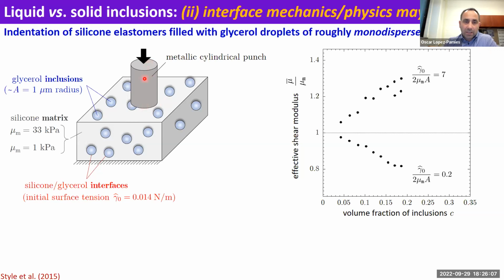So this is indentation of a block of material that contains liquid inclusions. And by changing the size of the inclusions or the surface tension, you may end up with systems that are stiffer than the matrix, or they are softer than the matrix. Let me say that again. The inclusions are liquid, think of water. But if you make them small enough, the interface becomes stiff, because spherical inclusions want to remain spherical, because of the surface tension.